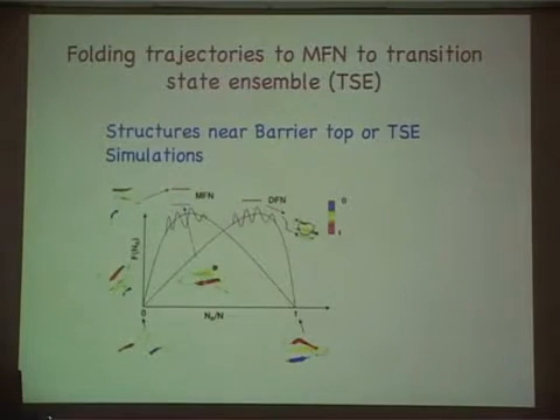One of the other things I should say is that the barrier from here to here in homogeneous nucleation theory is very, very large, and that's why the nucleation rate is quite small. But here the barriers are relatively small. In fact, I'll argue later it only scales as the square root of n times kBT, because if the barrier was really very large, folding time would be astronomical. That we know is not the case, and therefore these barriers are relatively small.